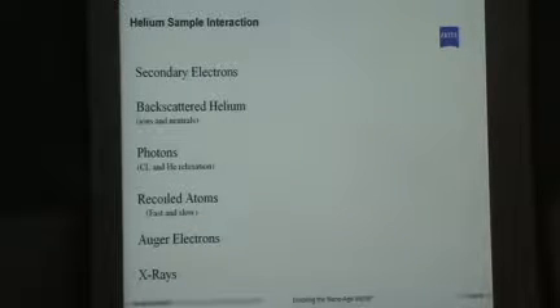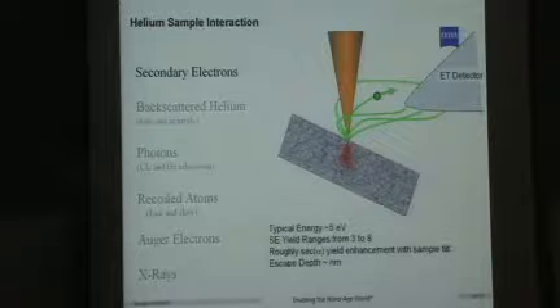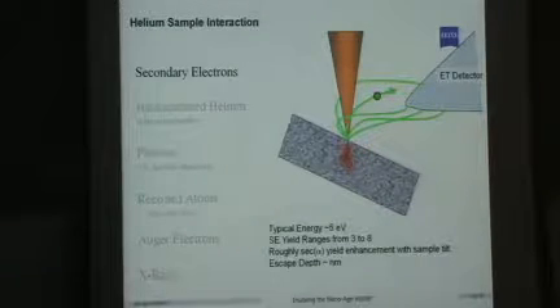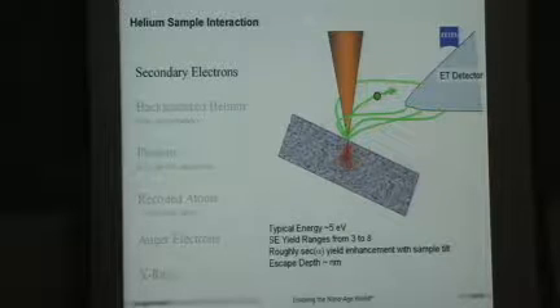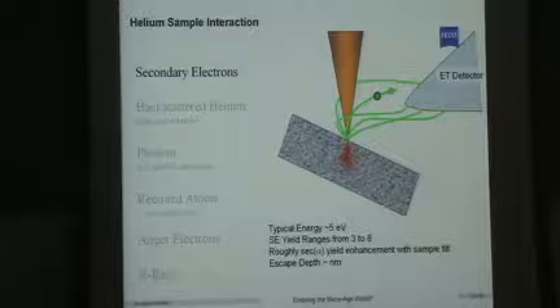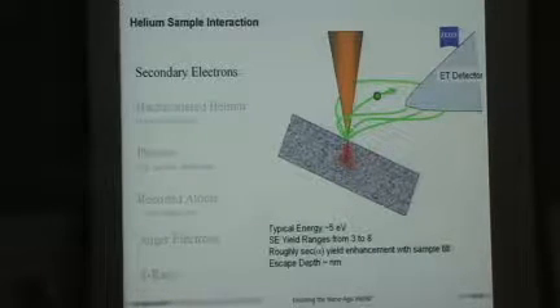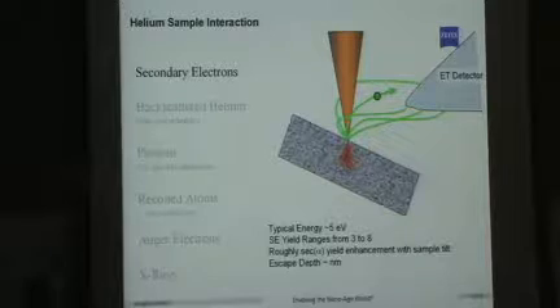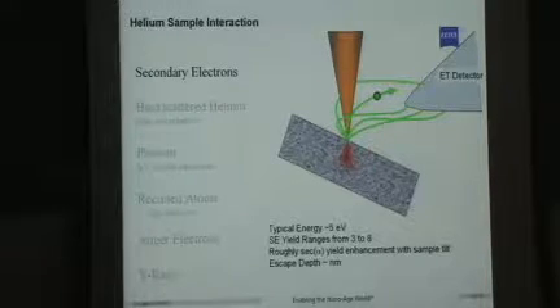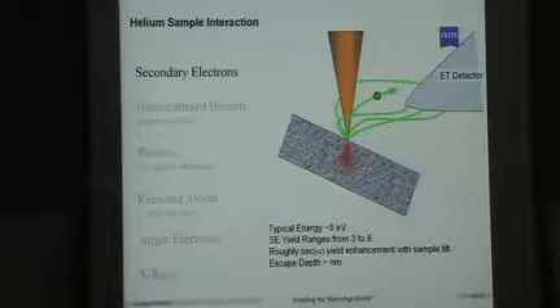These are all the particles that can happen. They're secondary electrons I just mentioned. Those ones are typically 5 eV. They're actually lower energy distributions than you would find in a SEM, and that's important to some applications. The secondary electron yield ranges from about 3 to 8, much higher than a SEM. Every ion coming in produces a good handful of secondary electrons that come out. And you do get the secant alpha yield enhancement, so you get nice topographic information. Their escape depth is just nanometers, giving you the shallow information.